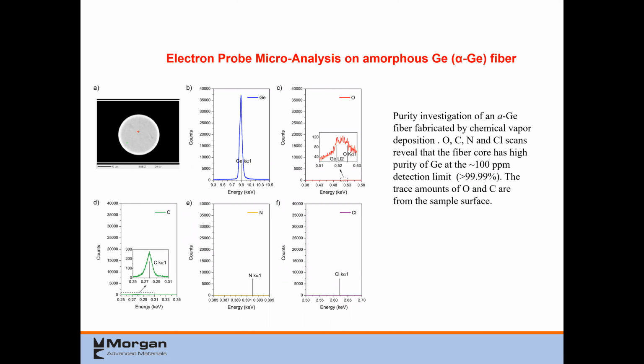This is some people who were growing germanium fibers, and they wrote a paper that they submitted to a journal showing that it was a pure germanium fiber. And one of the reviewers came back and said, well, how do you know you don't have a lot of oxygen and carbon in there? Because they're really tough to tell in an EDS, because basically carbon and oxygen are everywhere. So they brought it to me, and I looked at it in the electron microprobe, and I could show them that the count rates for carbon and oxygen were extremely low. So it was just a surface contamination and not part of the fiber itself. And so they were able to pass the review and get the paper published.